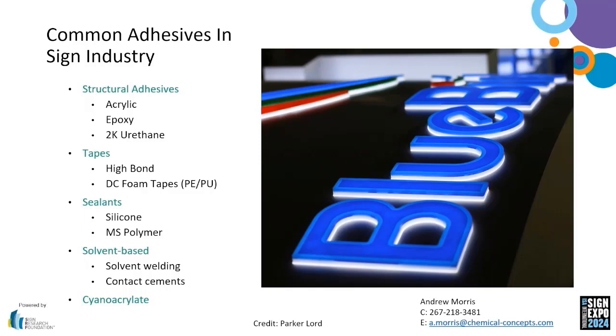The other thing that's really important is the cure curve. So epoxies tend to cure in a linear curve. So when epoxy is 80% through the cure time, it's about 80% cured. A lot of acrylics on the market use what's called snap cure technology, which means that within an hour or two, you're at 90%. So instead of that curve looking like this, it looks like this. And that's advantageous for you guys, because when do you need strength? You need strength right away. You don't need strength tomorrow. You want to be able to bond your parts and move them on to the next step in the operation. So that's another reason why acrylics have become so popular.